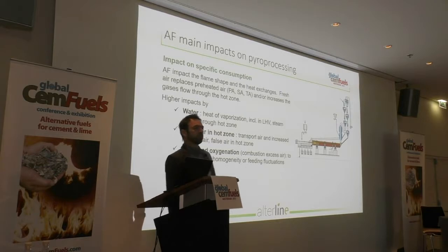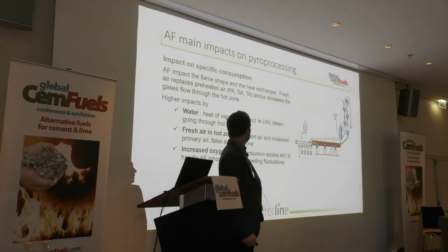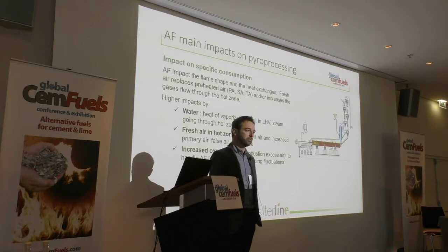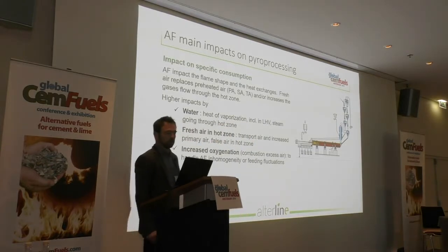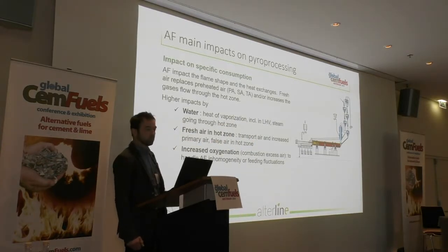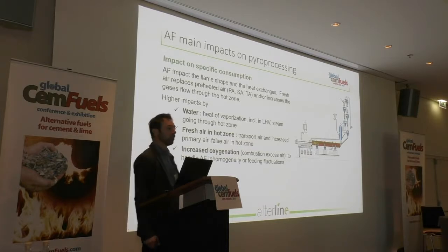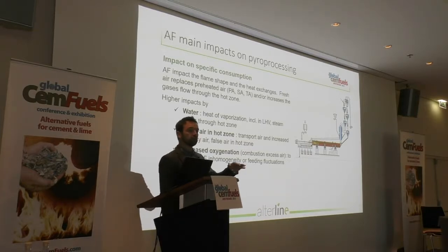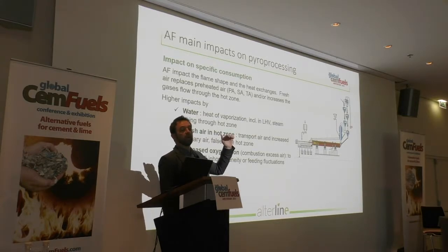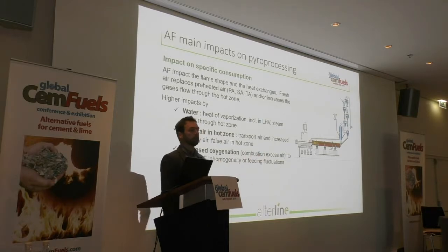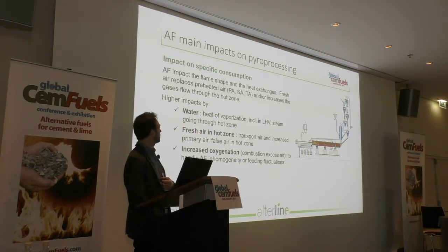So the first impact will be on the thermal consumption, mainly due to the water and the input of fresh air, and the increase of oxygen, because since you have some fluctuations, you need to increase the oxygen at the kiln inlet. It means you will have more gas and you will increase the consumption. The two big factors in this tree are water and increased oxygenation.